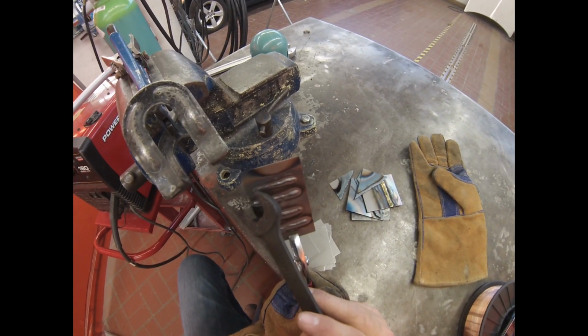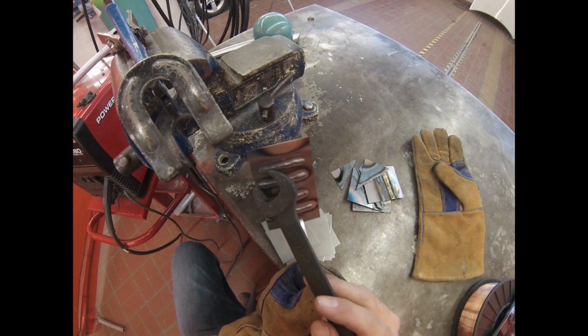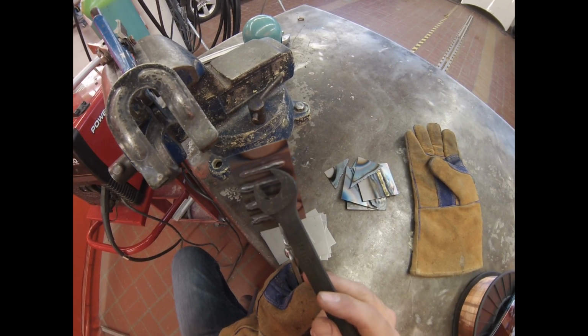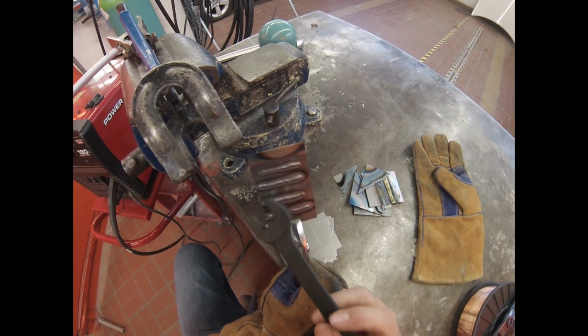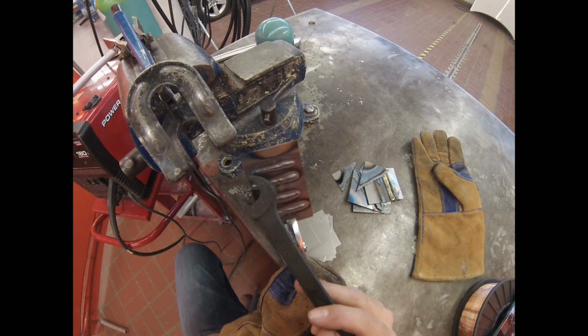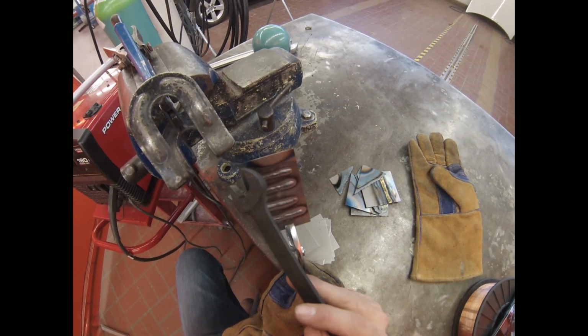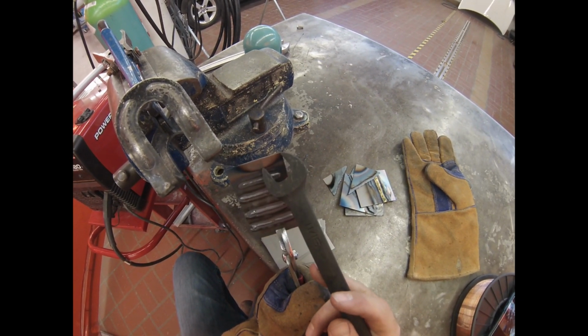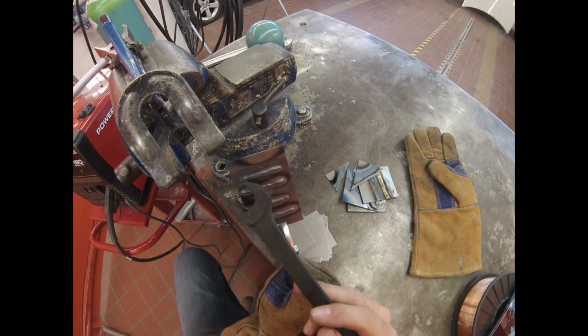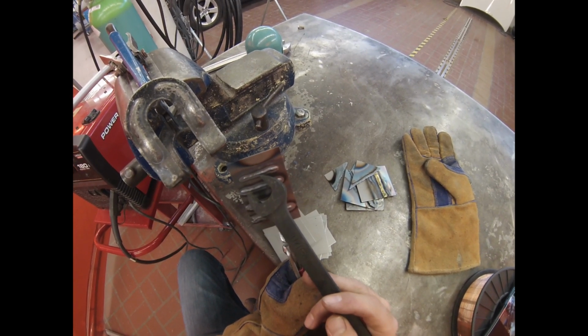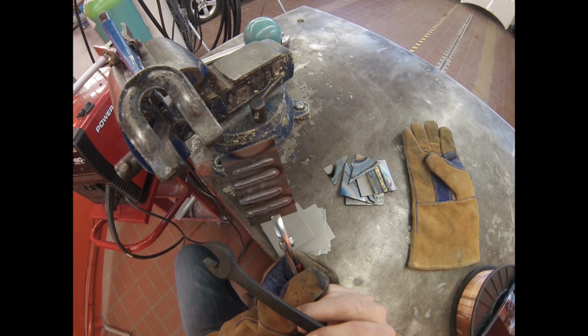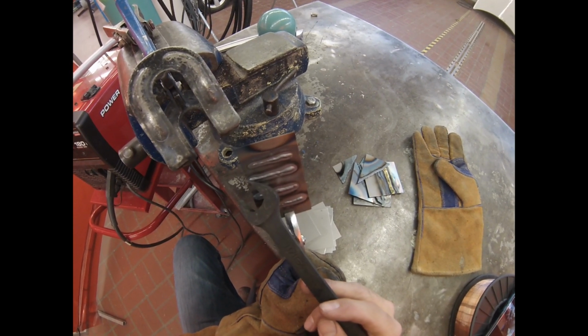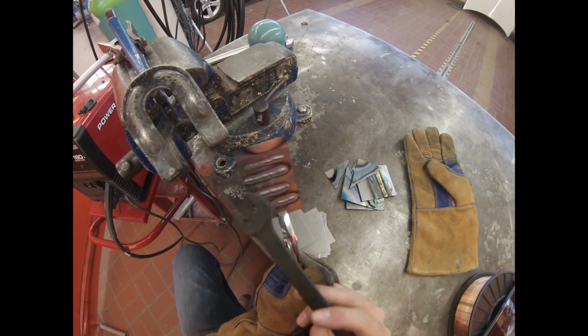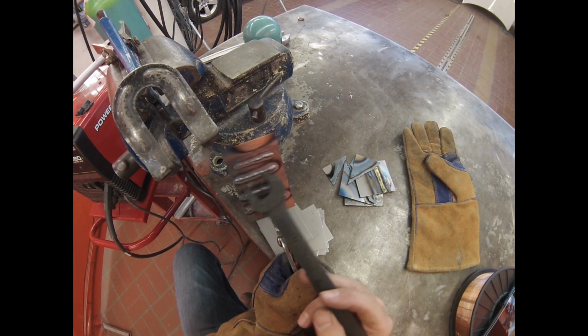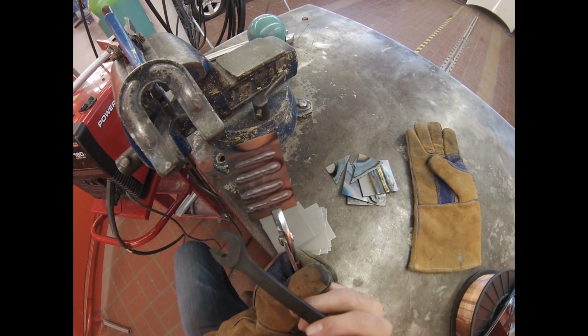And you can see there's not very much penetration, and it's not very even. And then it gets more penetration as it goes along. What's actually happening there is the coupon was cold, and as the heat melted and heated up the coupon, was preheating the coupon, then the weld started to sink in, right? This one you can see the weld is very even all the way across. And this is how you tell if you're doing the weld correctly or not. It's not the top, it's the bottom.